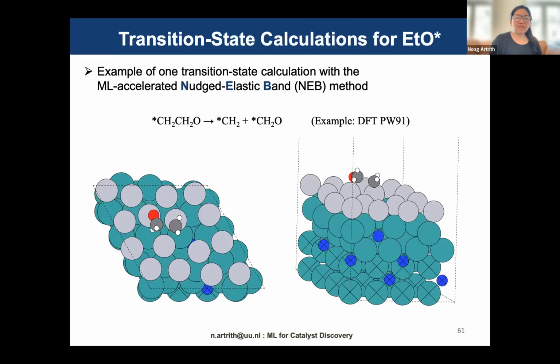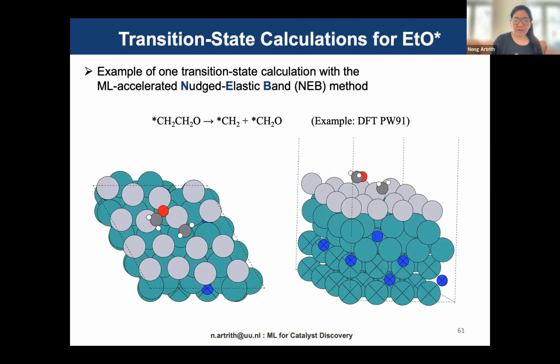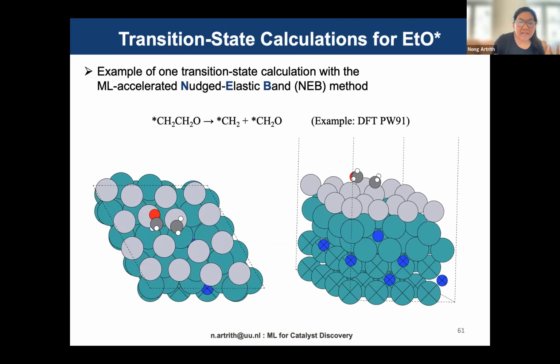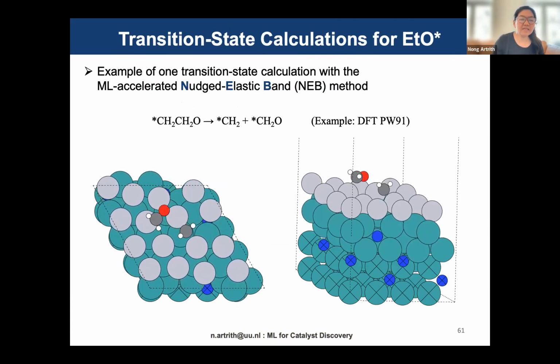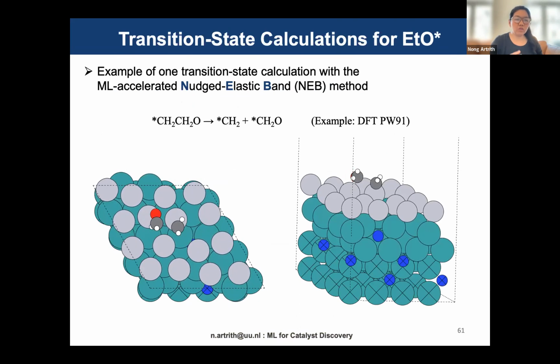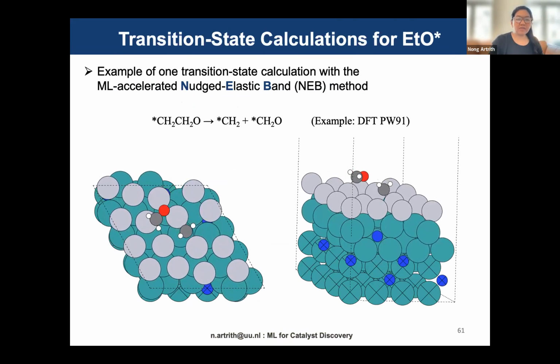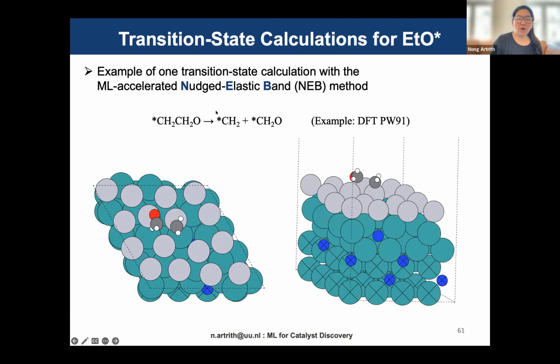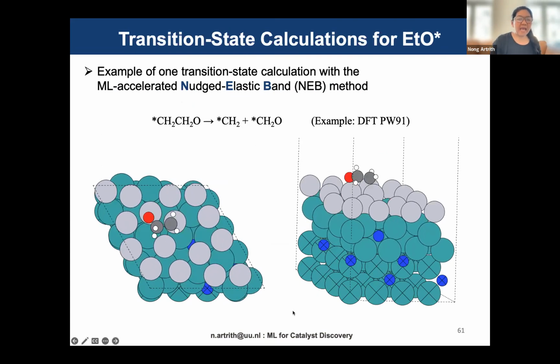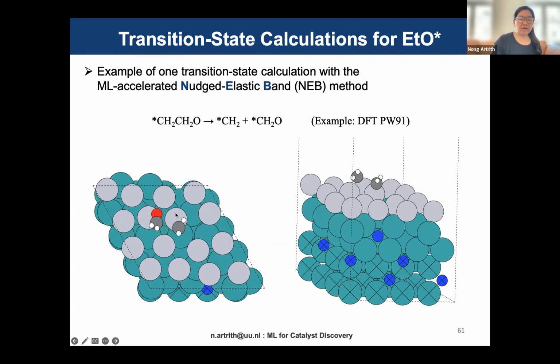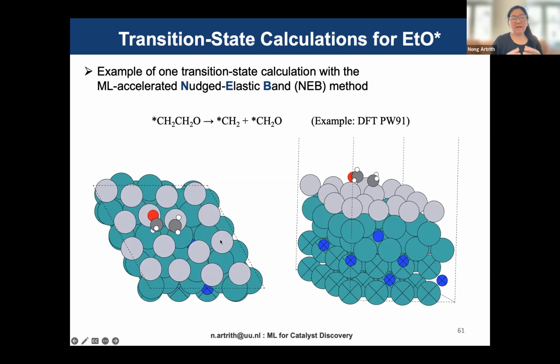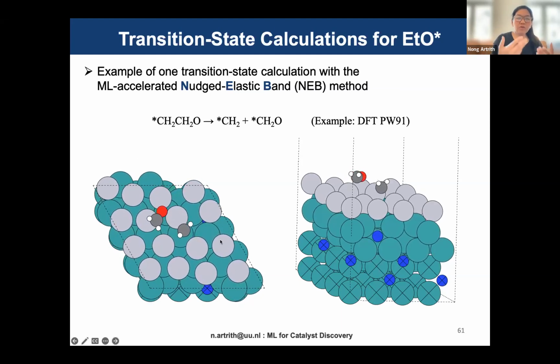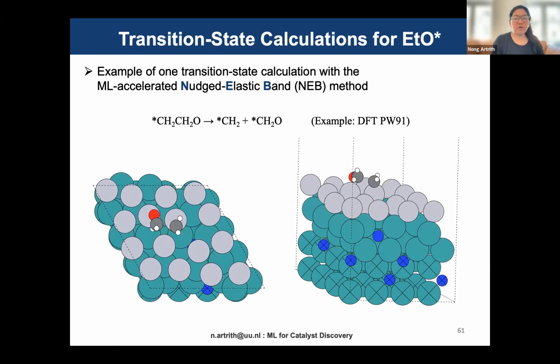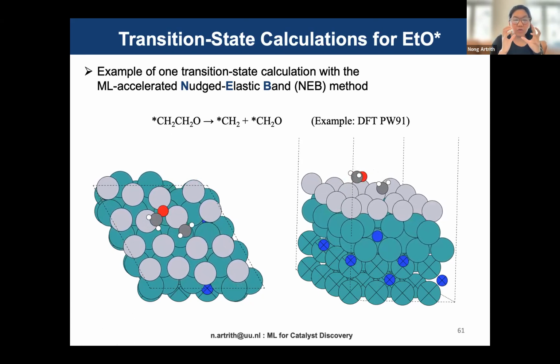So the first step, then, is we need to collect all of the NEB or the transition states to find the activation energies. So we also use a machine learning model to help find the path, for example, in this example, is it the C-C bond breaking of the ethanol? And I also show many different types of material. You can label anything, but then you need to really put the energies and also the activation energies in the database that we have.